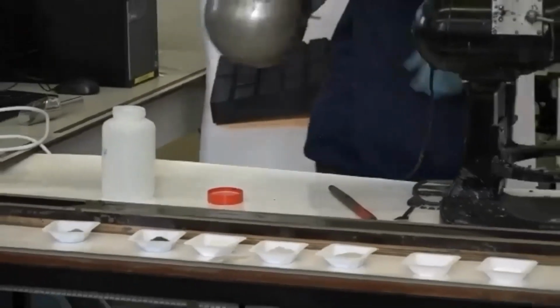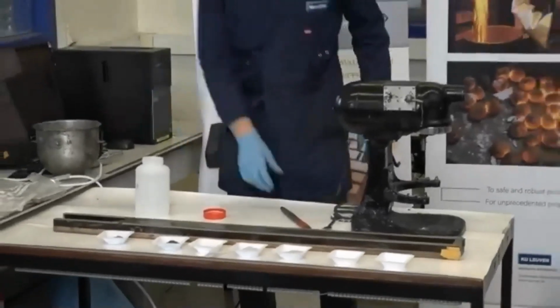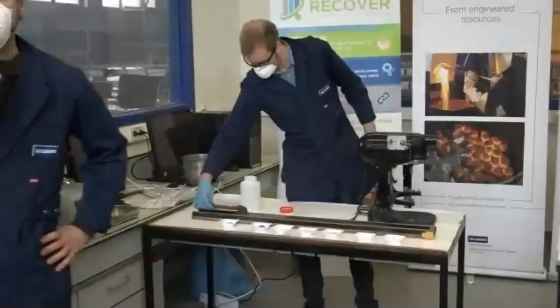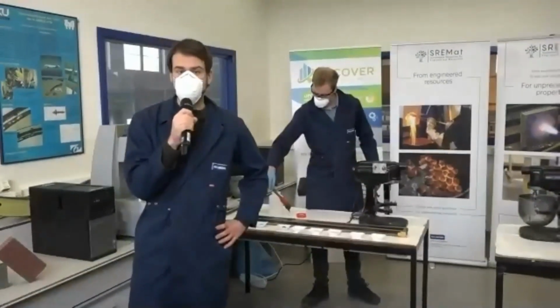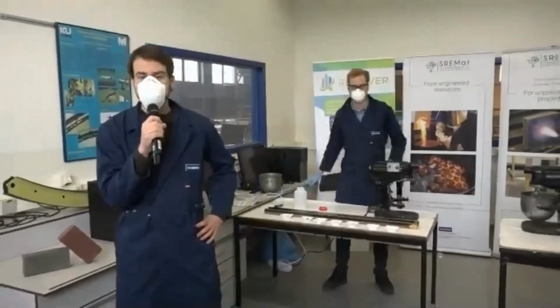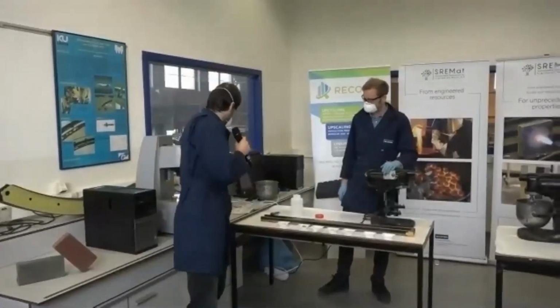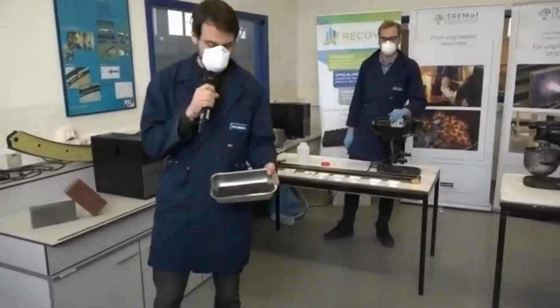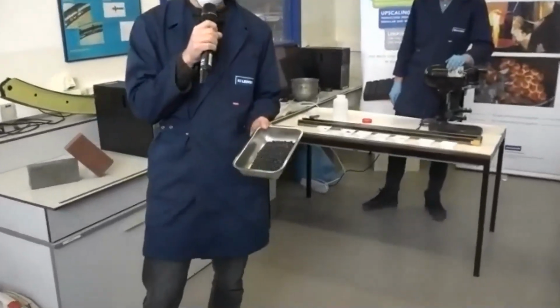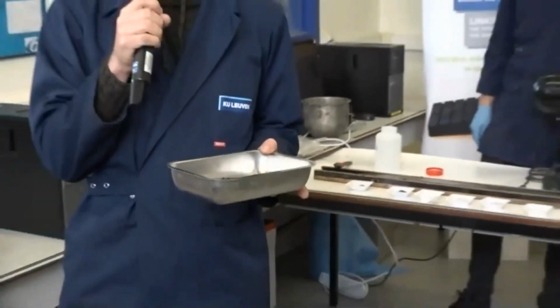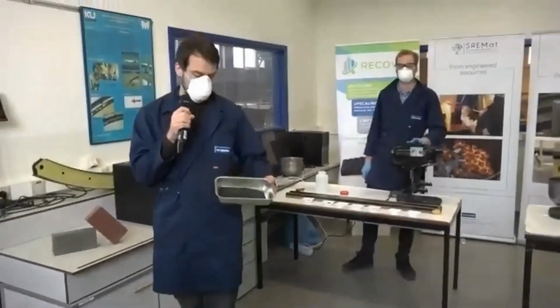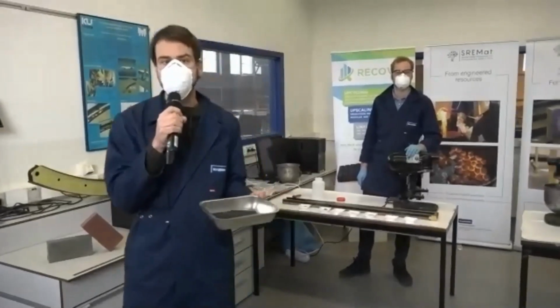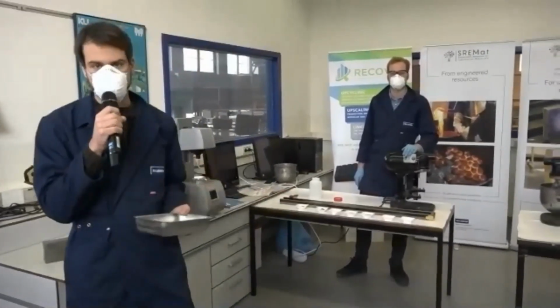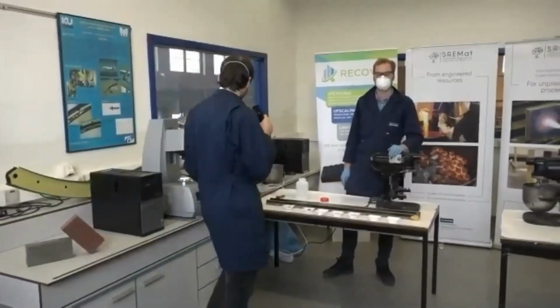And important to mention here again is that the main ingredient is an iron-rich slag. And as also mentioned at the beginning, we cannot only use Coronel slag or Boliden slag, we can also use vitrified bauxite residue. So that is actually vitrified bauxite residue that was produced for this project. You see now still it's relatively coarse. So the next step would be basically to mill this material to a fine specific surface area, similar to the other slags, and then it could be used as a precursor, for instance, for this hybrid binder mix.